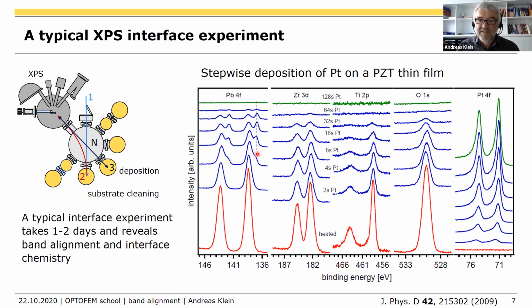So thermodynamically, PZT would not react with platinum to reduce the PZT and form platinum oxide. You also see the platinum is in principle metallic platinum. There is not much platinum oxide there. And the amount of lead, how much that is, well, that's hard to say. I would guess the lead also does not necessarily remain at the interface. It may, in principle, evaporate. But I will show more experiments on this later.